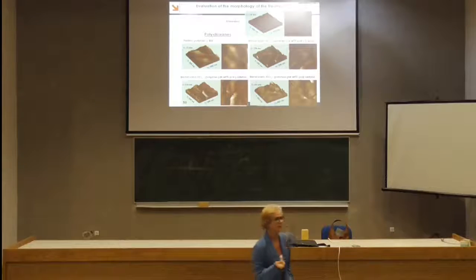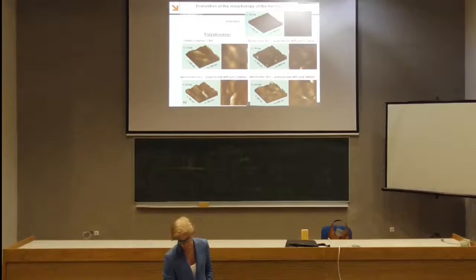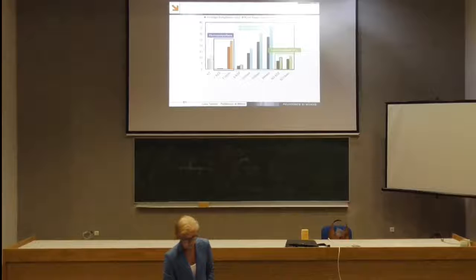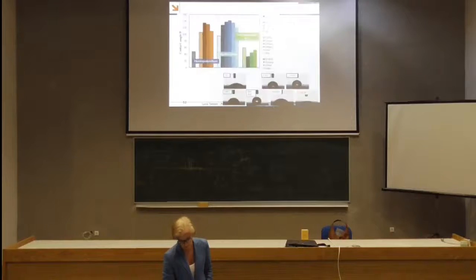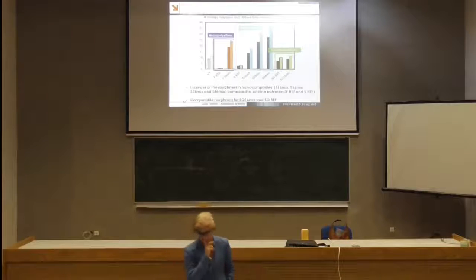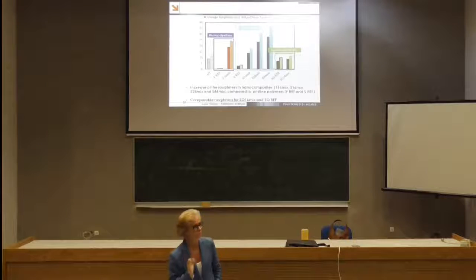It's not something that you can control, because normally with profilometry you can't see this, because these are nanoparticles. It's not a real roughness that you can perceive. It's something in the nano range. The increase of this roughness is critical for the water repellency. So to make the surface of the stone really protected.